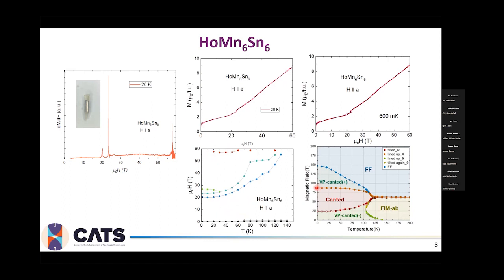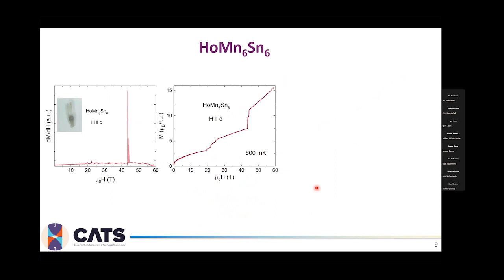But coming back to the more interesting part, with the magnetic field along the C direction, again here is the ampule with the crystal inside. When the magnetic field is applied along the C direction, we can see the 3 peaks and a very sharp peak around 45 Tesla. The interesting part, and the advantage of studying the magnetic susceptibility in that case, is that we can actually see what that possible critical endpoint will look like in this material.